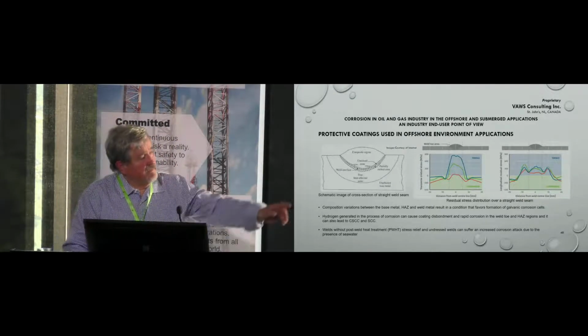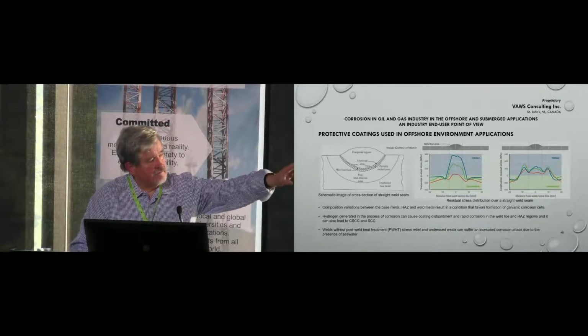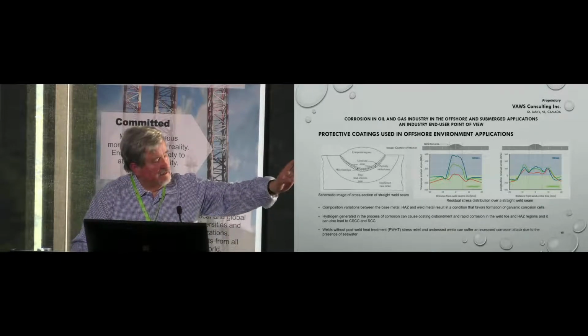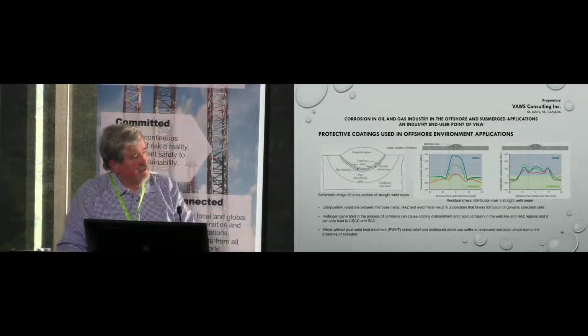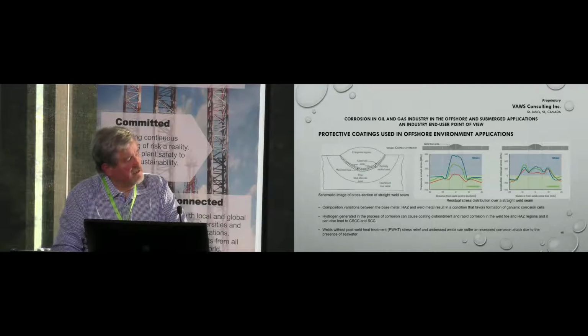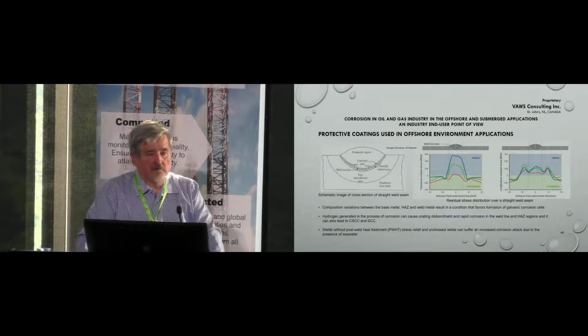And you can see on those pictures on the left, one is the transverse direction, one is longitudinal direction. On the straight weld, you can see the differences in stresses. And when you have that kind of differences in stresses, you will have significant corrosion. The proper way would be to stress relieve all the welds, weld only materials which are properly preheated, and that's expensive and sometimes not possible.